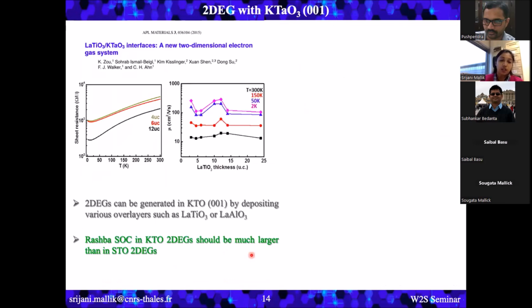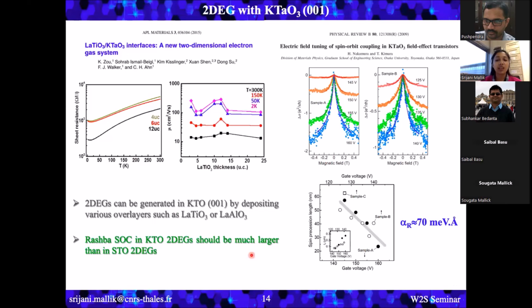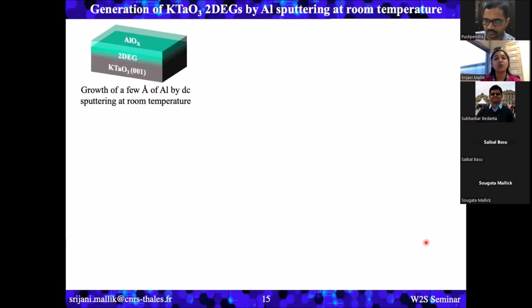It's also possible to achieve a two-dimensional electron gas by depositing other perovskite materials similar to STO. And it's expected that the Rashba spin orbit coupling in KTO 2DEGs should be much larger than in STO 2DEGs. There were some preliminary reports where they tried to find the Rashba coefficient for KTO 2DEGs, and they found it to be 70 millielectron volt angstrom. So long ago, the preliminary calculation for alpha was already higher than the maximum achieved for STO 2DEGs. I just showed that for a specific gate voltage, the maximum for STO 2DEGs is 50 millielectron volt angstrom, whereas there were already reports of 70. So it's nice, and with this motivation, we started to work on the potassium tantalate 2DEGs.